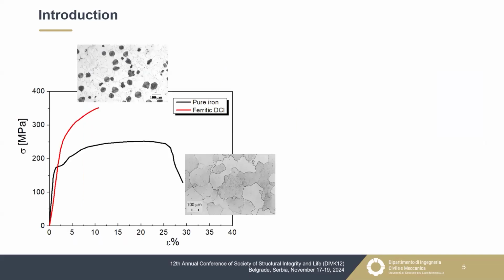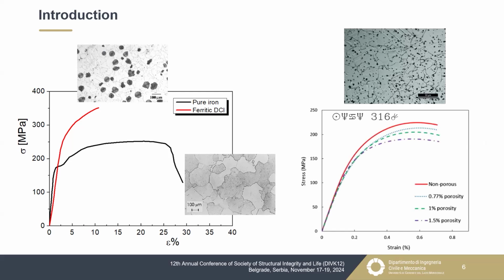If we compare, for example, ferritic ductile cast iron with pure iron, more or less the matrix is the same, because in ferritic ductile cast iron, in the ferritic matrix, we have only iron, and these balls of graphite embedded in this matrix. We can see that the behavior improves. And if we compare, for example, an austenitic stainless steel, we can see that an increase of porosity implies a decrease of the stress strain behavior.